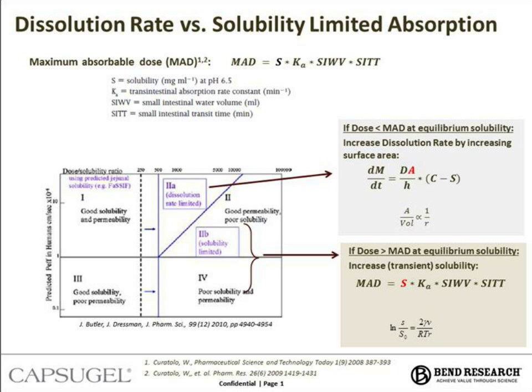There are varying perspectives in the scientific literature, but I think there's a bit of a consensus these days that the size crystals obtained using top-down attrition processes that I just described, citing the 150 to 400 nanometer range, mainly increase the dissolution rate due to the increase in surface area, as shown in the gray box there, and perhaps by decreasing the diffusion layer thickness, h, shown in the denominator of that equation. But usually not increasing the solubility of the drug.